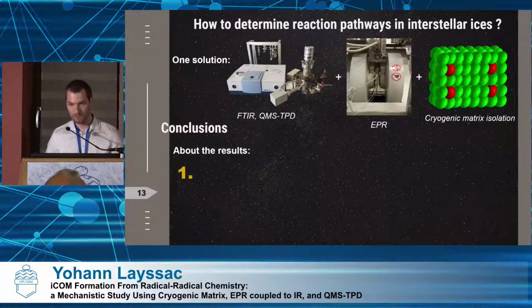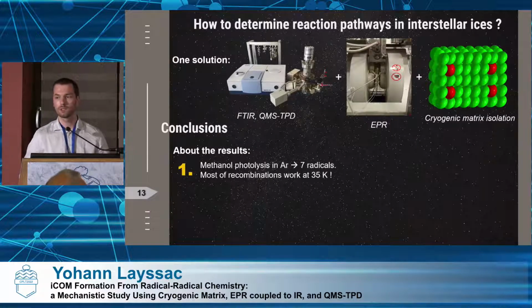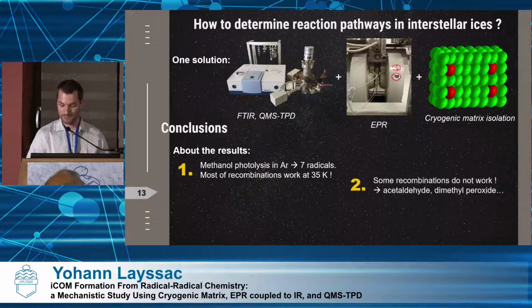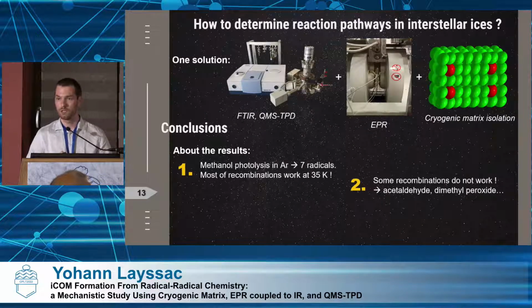About the results, we saw that photolyzing methanol, we get 7 different radicals. Most of the recombinations work at 35K, and I put a warning there, it works at 35K because the desorption temperature of argon, when the radicals can meet, is 35K, and we didn't test lower temperatures. But maybe more interestingly, some recombinations do not work, meaning really that radical plus radical reactivity is not always a straightforward mechanism to think about in interstellar ices. There are sometimes other kinds of mechanisms.